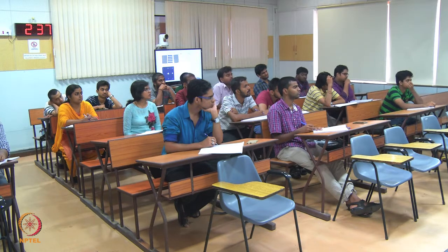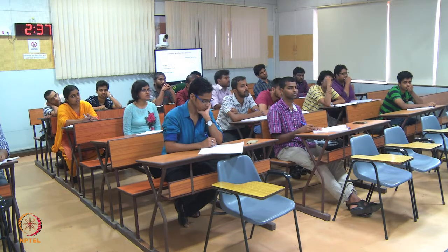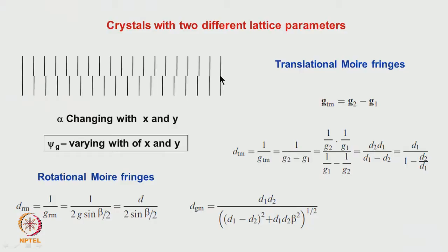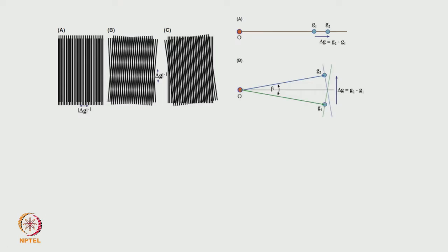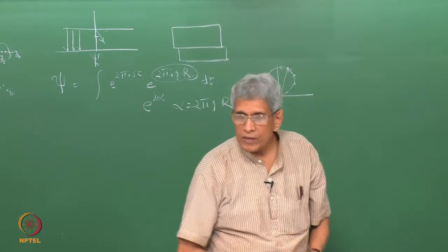But when those lattices are kept close to each other, at some distance you find that some lattice planes will match at some periodic interval, that's all. Diffraction is taking place from each lattice separately. So this phenomenon will give rise to diffraction spots like this, which are separated. When we put an aperture around it, the interference fringe contrast essentially comes from the top layer; the beam comes, and when it sees the bottom layer, the amplitude of the wave is going to change. So the net amplitude is something like considering an interference essentially. Okay.